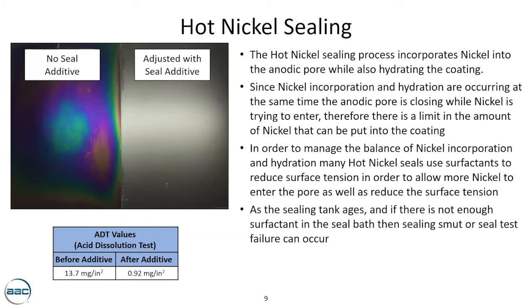All right. This slide discusses hot nickel sealing. What you'll see here again is another image where you have a part that is sealed in a hot nickel bath that doesn't have enough of the surfactant or seal additive. And the part on the right is a similar panel that has been immersed in that same bath. However, an addition of the correct surfactant has been made. The iridescence associated with the no seal additive part is a phenomenon wherein you're incorporating nickel into the coating and you're trying to hydrate it, and it reflects light and results in iridescence. That's usually an indicator of, yes, I have sealed the part, but I clearly do not have enough of the appropriate additive chemistry to manage the cosmetic look of it.